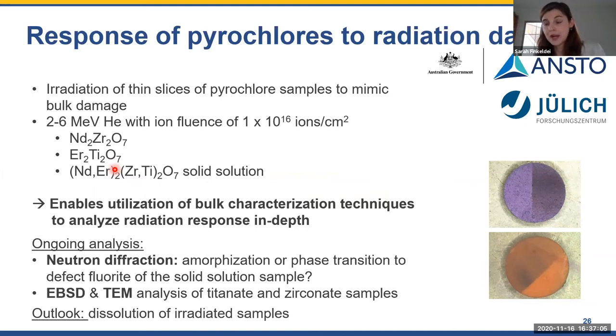What we did is we irradiated those two different ceramics, a neodymium zirconate and an erbium titanate, with helium ions to mimic alpha decay. And we prepared very thin samples, and that allowed us to basically use bulk characterization techniques to analyze the radiation response in depth. So we damaged the entire material, and we are currently in the process of evaluating our neutron diffraction data on these irradiated specimens.